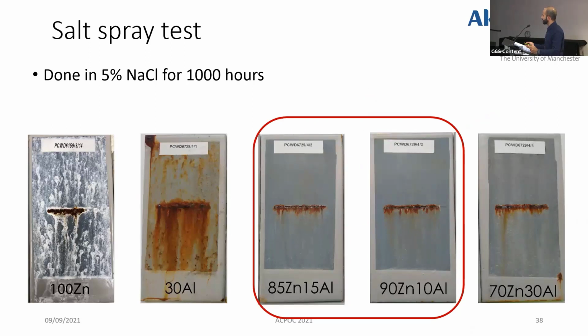The salt spray test was done in 5% NaCl for 1,000 hours. And you can see there is relatively better performance against corrosion for 85 zinc 15 aluminum and 90 zinc 10 aluminum in comparison with the control one and with the 70 zinc 30 aluminum. This offers almost no galvanic action at all, only a slight barrier action at the beginning of the service, and then it failed.